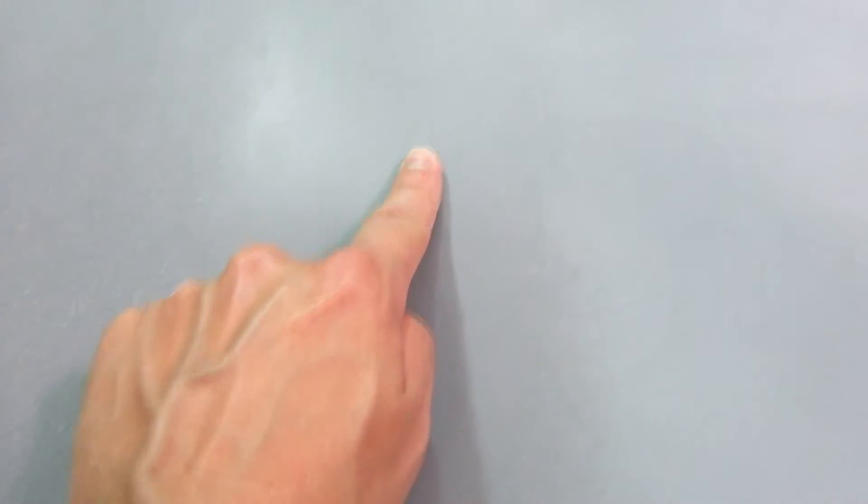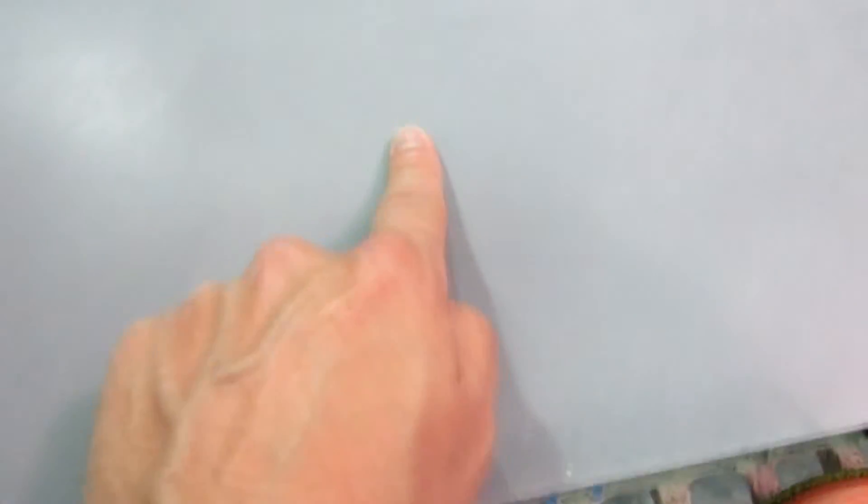Here's a close-up of the surface. So the surface is clean and dry. I wiped it down with some acetone to remove any moisture effects. This area was with the 400 grit wet dry sandpaper, sanded wet. This is the 200 grit diamond pad, sanded wet on an air sander. And this is the untouched melamine textured concrete.